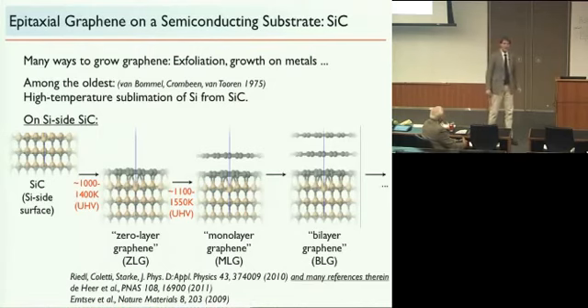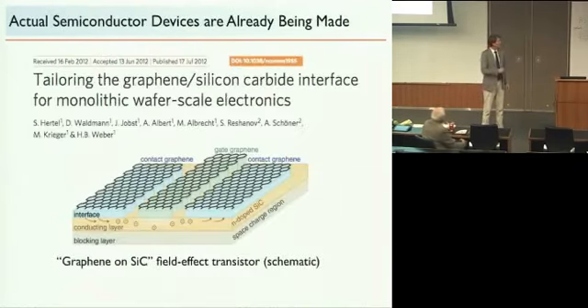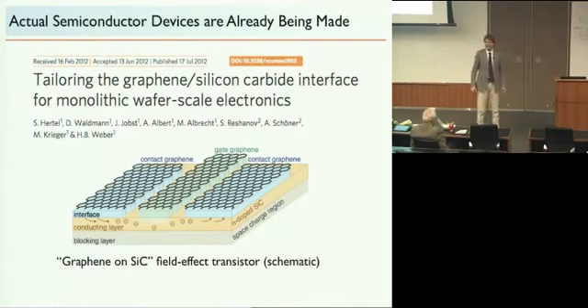Now, this is a practical thing because it really creates graphene directly on a semiconducting substrate, so you can use the normal tools of semiconductor science to do something with it. This is an example of a field effect transistor that was made by just using graphene as the kind of metal contact to the transistor and making the transistor out of silicon carbide. Just briefly, what is labeled contact graphene here is the monolayer graphene that I just showed you. This gate graphene here is the same thing, but additionally there's a layer of hydrogen atoms intercalated that electronically insulates it from the substrate. But that, in a nutshell, in this paper produces a current voltage characteristics that looks like a field effect transistor. So this is useful.